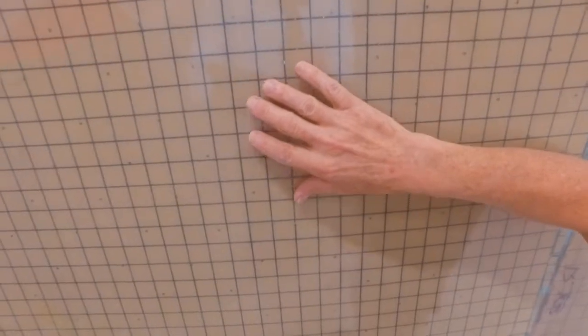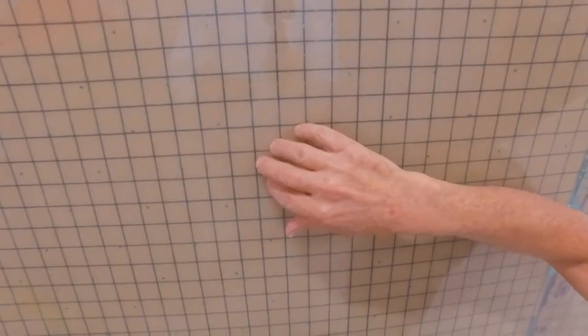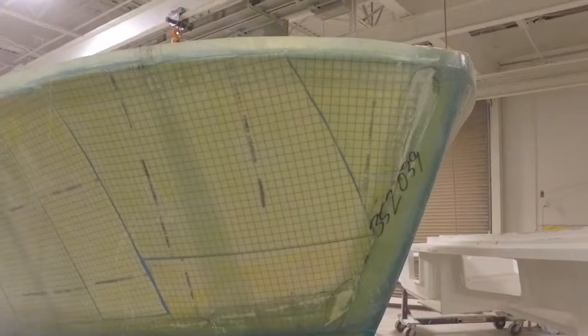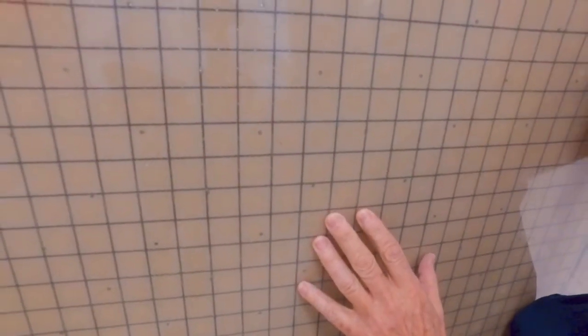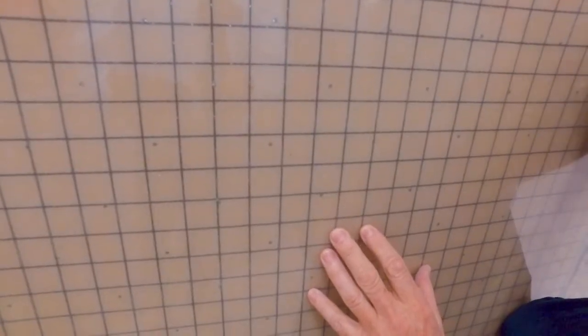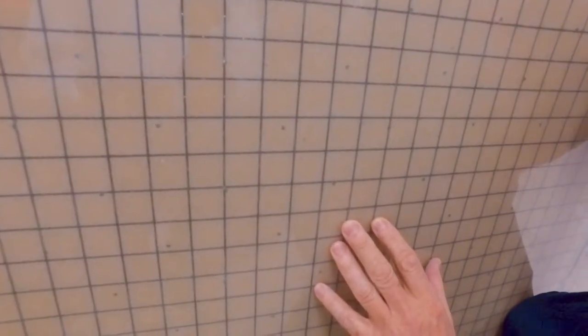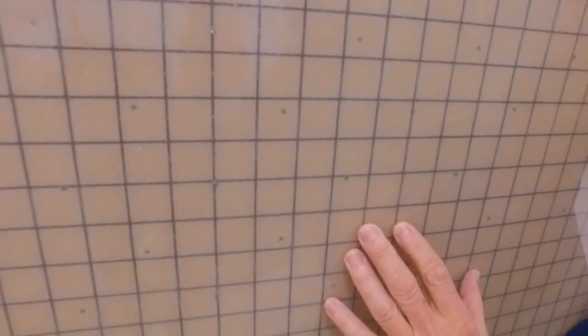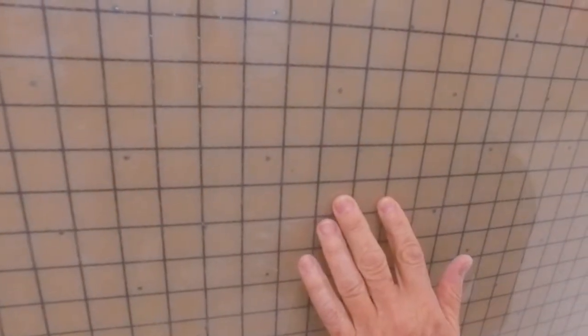So this is an example of infusion working as intended. The fact that there's a 35-ounce quadraxial on here that you can't see is an indication that both the epoxy and the pressure from the vacuum bag is working as intended. One atmosphere of pressure from the vacuum is equivalent to 2,116 pounds per square foot pushing on the inside of the mold. But the clarity that you see here is a good indication that everything's working according to plan.